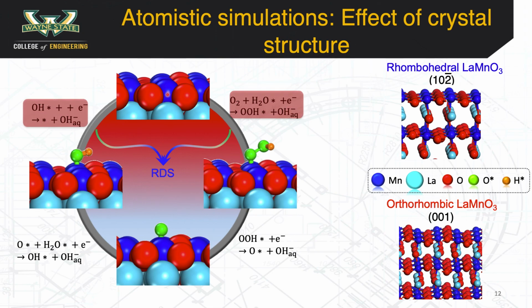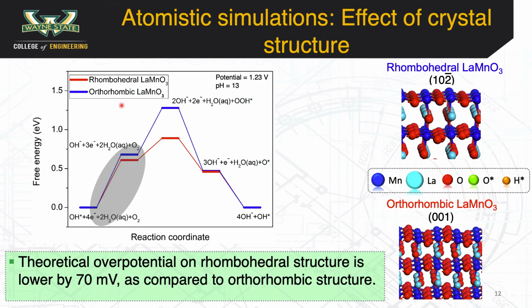It has been well established that for catalytic systems that are limited by weak adsorption of oxygenated intermediates, O2 protonation to OOH is the rate limiting step. While catalysts that have strong binding of oxygenated intermediates are limited by OH removal to generate a clean site. We then convert these atomistic simulations into a free energy diagram. It is observed that on both rhombohedral and orthorhombic LaMnO3, OH removal to generate a clean surface site is the potential determining step.